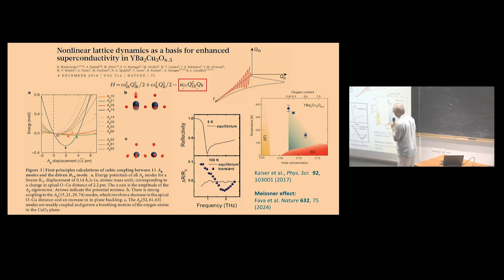How is it measured? You must imagine it is on a picosecond time scale. So it is determined from infrared reflectivity. Again, they can calculate infrared reflectivity, just the transient one, and here is the change of reflectivity in equilibrium. Okay, we have no change, and with the transient effect, you have just an increase and decrease. Why is it like this?